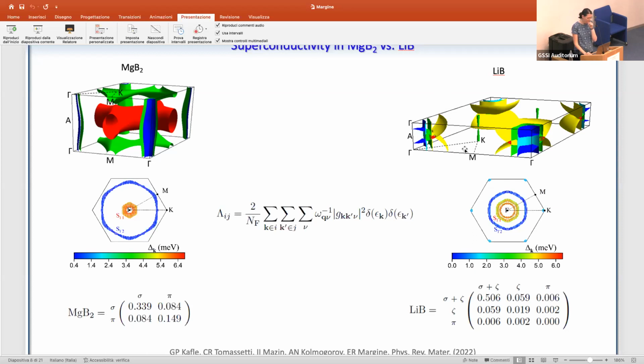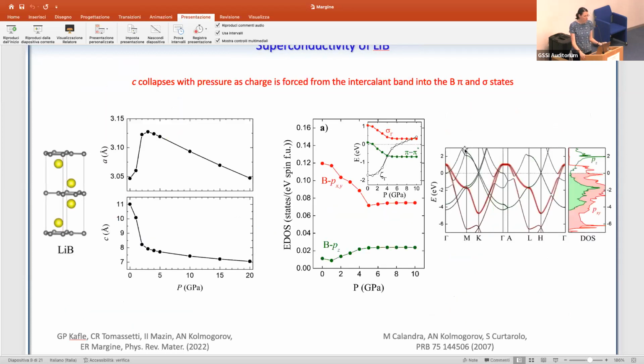One important thing in lithium boron, as I mentioned earlier, is that there is no contribution from the pi states because accidentally the Dirac cones fall exactly at the Fermi level. So in this original study, it was suggested that pressure, and in fact also doping, could move the Dirac points such that the density of states at the Fermi level coming from the pi states can be improved.